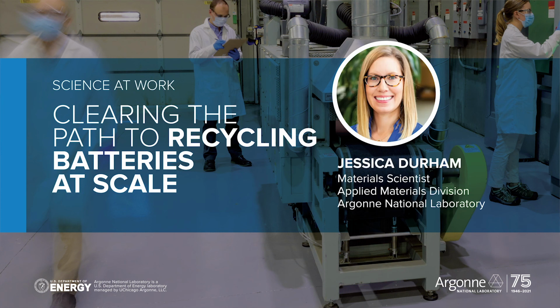Thank you, John. That's a good question. I would say two of the biggest things are purity and performance of the recycled material. For instance, industry typically has strict purity standards of 99.9%. In some cases, you can even add a few more nines to the end of this. And performance-wise, we've talked to industry, and they prefer to stay within a few milliamp hours per gram of the delivered capacity over time. And this is really important if you're using 100% recycled material in a battery.